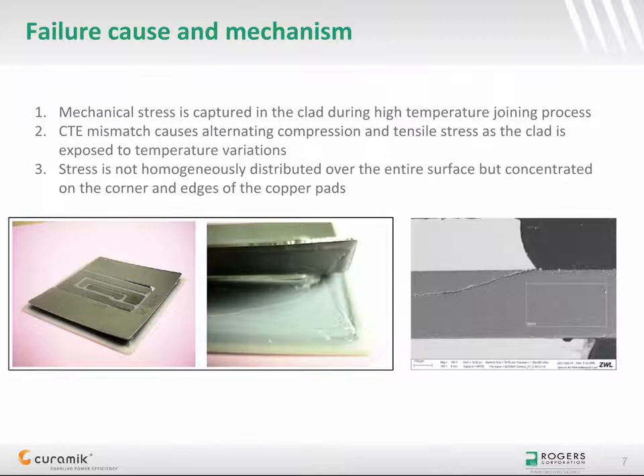Later, under real-life conditions, substrates will be exposed to significant temperature swings because the ambient temperature may vary and the junction temperature of the semiconductor devices will change as they switch on and off the load. This will cause alternating compression and tensile stress in the clad of material. This stress is not homogeneously distributed over the entire surface, but concentrated on the corners and edges of the copper pads, and ultimately will cause edge cracks in the ceramic, also well known as conchoidal fracture.